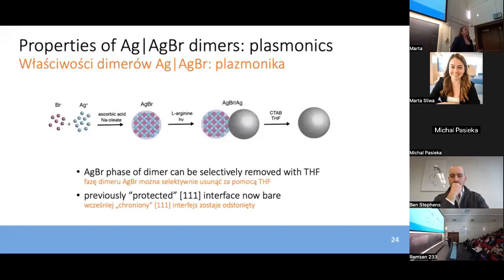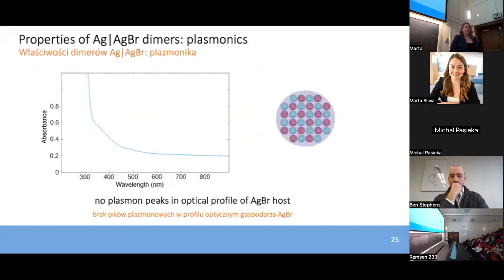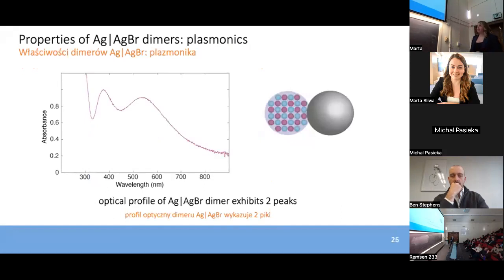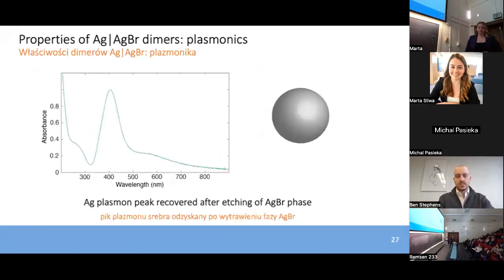So we compared the UV-vis profiles of these species at the three key stages of synthesis: host, dimer, and the particles that we isolate. We saw no plasmon peak for the silver bromide, as expected. Two new peaks in the plasmon profile for the dimer, which I had previously shown you. And when we remove the silver bromide phase to yield that single nanoparticle, we see an absorbance profile that we would expect for a standalone isotropic nanoparticle of this size, with a sharp peak at 405 nanometers. So we recover that plasmon for the silver nanoparticles after removal of the silver bromide phase.